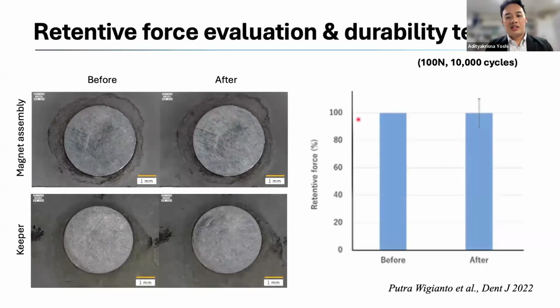We performed the basic experiments and basic evaluations of this new magnet assembly structure and performed a durability test of 10,000 insertion and removal cycles with 100 Newton load. And we found that there was no notable deformation on the surface, and the retentive force doesn't change after those cycles.